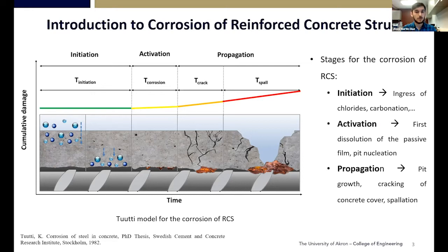As everyone knows, concrete works perfectly under compression, but not tension, inducing some cracking. After the first crack starts, more chlorides and water can get inside the concrete more rapidly than just by mass transport through the concrete, and more oxide scale can be formed, ending up with a huge tensile stress that by spalling will take out the concrete cover, and now our rebar is exposed to the chlorides.